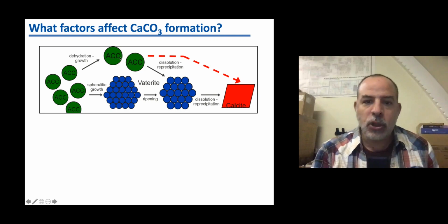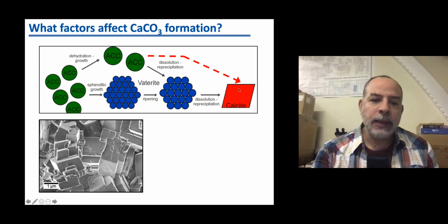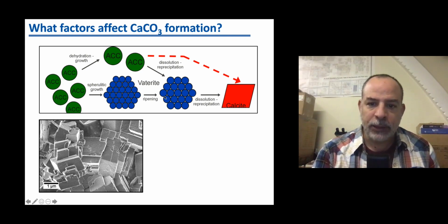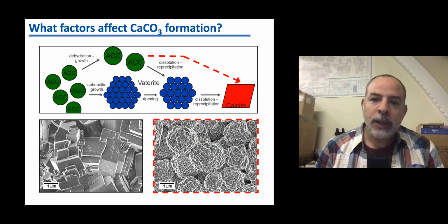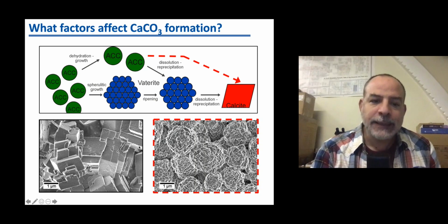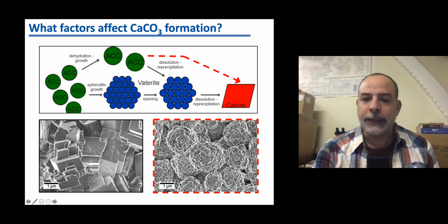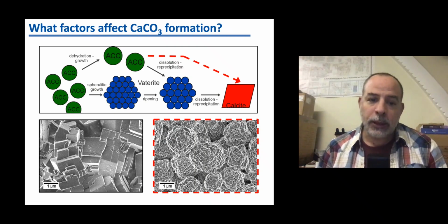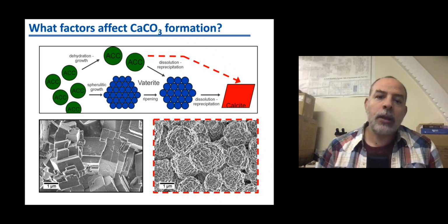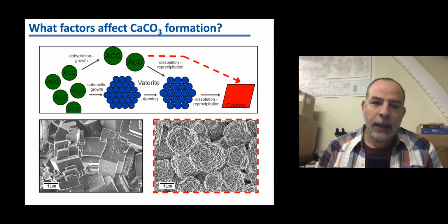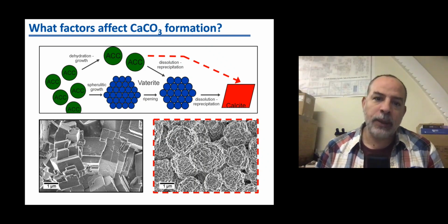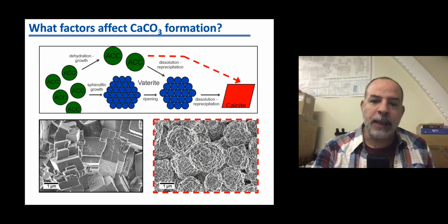So what we see here is what is shown in this red line. While in the first case we were forming amorphous calcium carbonate, then vaterite, and then calcite, and this is what is shown in this picture at the bottom. Then in the second case we have this amorphous phase that breaks down and transforms directly into calcite. So the solid looks completely different, and it looks completely different because it crystallizes via spherulitic growth. Here we have calcite formed via dissolution and recrystallization, and here calcite formed via spherulitic growth. Therefore, the surface properties of these crystals are completely different, considering that they have the same composition and the same structure, and they were formed from the same fluids, but only this mixing difference and this difference in starting pH can completely change the mechanism of formation.